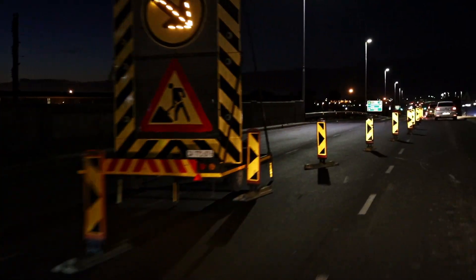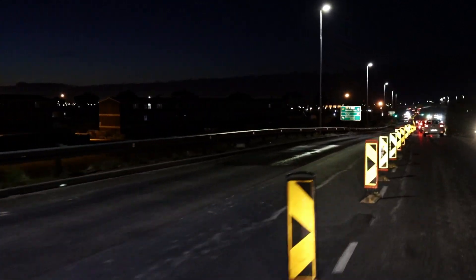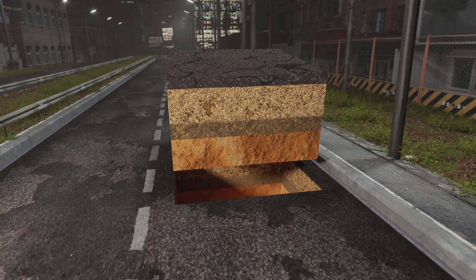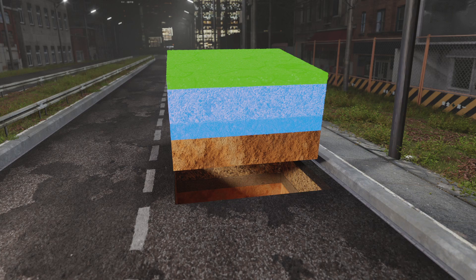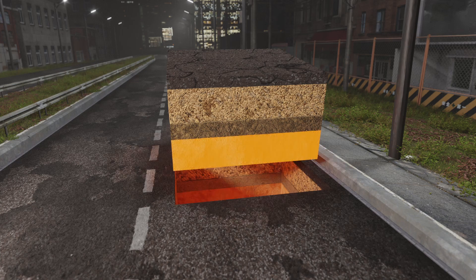Conventional rehabilitation and replacement of pavement materials mean road lanes will have to stay closed for days, even weeks on end. BSM, or bitumen stabilised material, provides a unique solution to this difficult problem by allowing us to rehabilitate the road to a depth of 370mm at night and having the road open to traffic before the morning rush hour. The existing road consists of 80mm of asphalt on varying layers of granular material, including a water-bound macadam layer. This pavement structure protects the underlying sand subgrade.